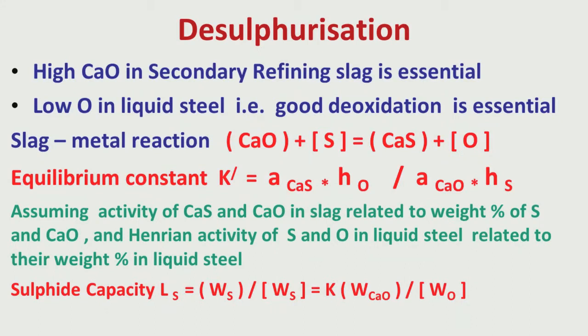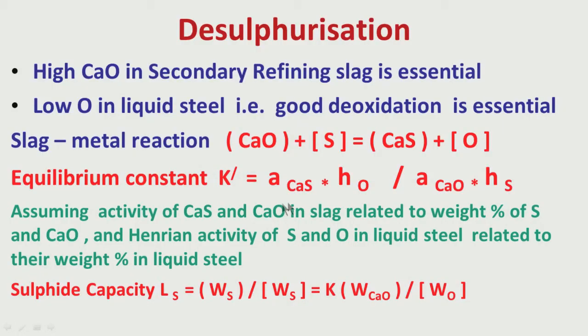Then I have talked about desulphurization and I have mentioned how CaO in slag is very important. We must have about 50 percent CaO in the slag in secondary refining processes, and the basicity — that means the ratio of CaO to SiO₂ in the slag — should be at least 3, preferably more than 3. The sulphide capacity is proportional to the weight of CaO in the slag and inversely proportional to oxygen content in liquid steel. So dissolved oxygen in liquid steel has to be low to get good desulphurization. Good deoxidation is a prerequisite and a necessity for getting good desulphurization.